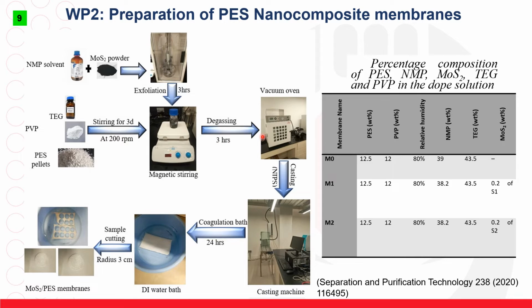After the mixing phase and achieving a homogeneous blended solution, we degassed the solutions using a vacuum oven and cast the solutions using a casting machine, which had a humidifier to achieve a proper isotropic membrane. And these were the blending weight percentages.